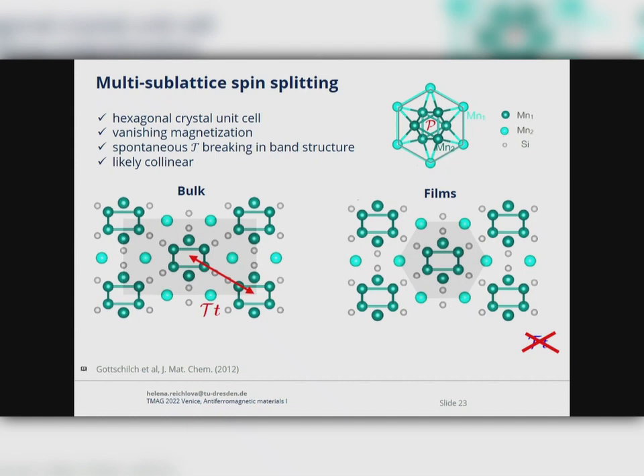So these four manganese, which are the only ones which are magnetically ordered, are actually doubling the magnetic unit cell. So here the time reversal symmetry is preserved, and this is completely inconsistent with the neutron data reported here. This is opposite to the thin films, where the hexagonal unit cell is stabilized. There is no reason that there would be any doubling of the magnetic unit cell. And here when I flip the spins, I cannot do this shift as here, so therefore the time reversal symmetry is broken.